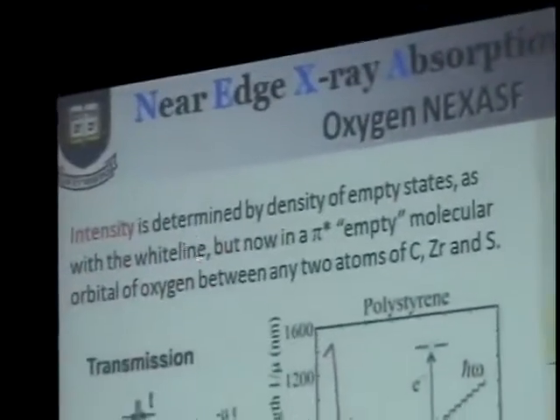But I want to make 2 statements about it. Up here, about the intensity: the intensity is determined by the density of empty states, very much as with the white line, but now the density of empty states in this vacant pi star orbital, and that's true whether it's involved in bonding to carbon or zirconium or sulfur. But the edge binding energy shift is determined by changes in electron density of the core here. In other words, the more positive charge I put on the core, the more I drag this to lower energy. And so if there's a shift in energy, meaning that this energy is greater, that would mean that this level is at higher energy. Okay, so that just reminds you of how NEXAFS is different from other X-ray absorption spectroscopy.